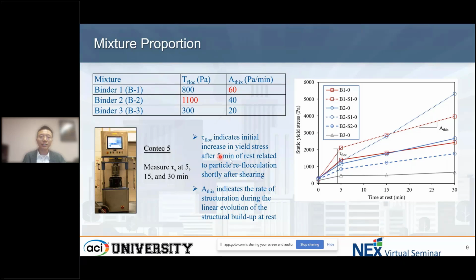floc value, which is the increase in yield stress after 5 minutes of rest. In this figure, it is this value. You see the floc, this value, and the A_thix indicates the rate of structuration during the linear evolution. In our case, it is the structuration rate during 5 to 30 minutes. It means this.